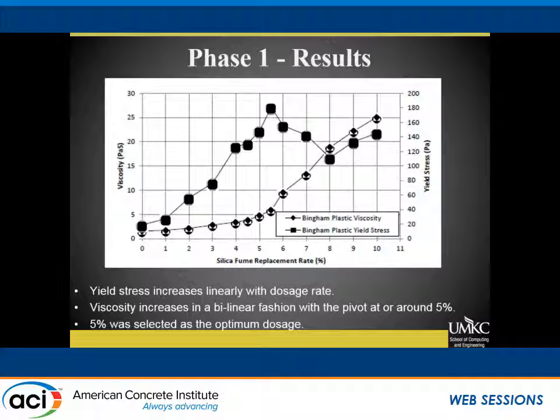So looking at this, we'd anecdotally heard that around 5% was the sweet spot for Pervious, at least for regular dosage rates, not adjusting water reducer with dosage rate. Okay, I'll buy it. Somewhere around 5 and 5.5%. We do have some differences as to the rest of it. So we said 5% is good.